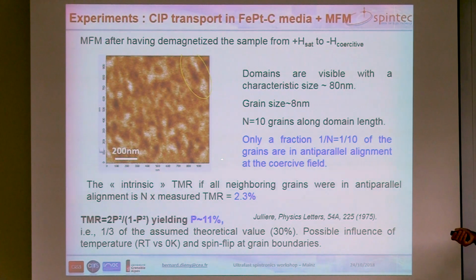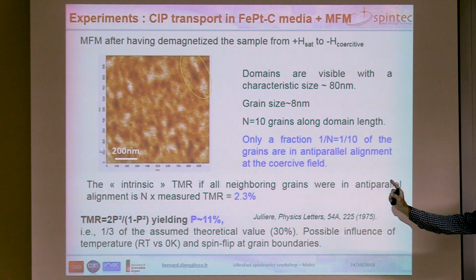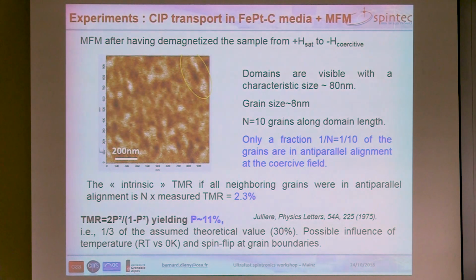So for this, we made MFM experiments, and you see that we see some domains here in the recording media at the coercive field, and the size of these domains is typically of the order of 80 nanometers. So considering that the grain size is 8 nanometers, this means that in this domain we have typically 10 grains up and then 10 grains down and 10 grains up and so on. So only 1/10 of the grains are in antiparallel alignment. So it means that we have here, when we measure the TMR, a dilution effect.